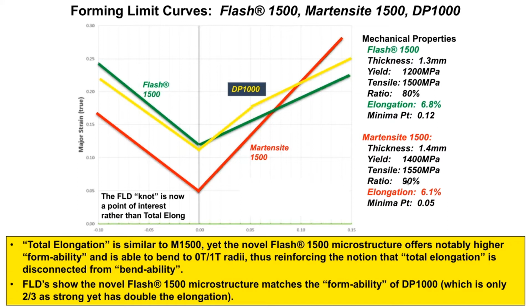So even though flash's total elongation is similar to M1500, the local formability and the biaxial formability actually make flash form just as well as a DP 1000. That's pretty interesting. So we had to put this to the test working with auto OEMs, and we have actually gone out and formed parts that in the past had been limited to DP 780 or DP 980, yet we're cold stamping them in prototype tools with flash 1500 and flash 1600.